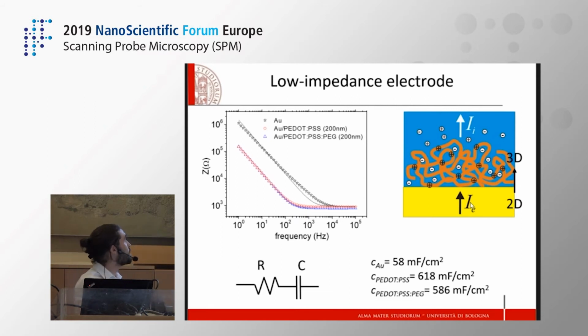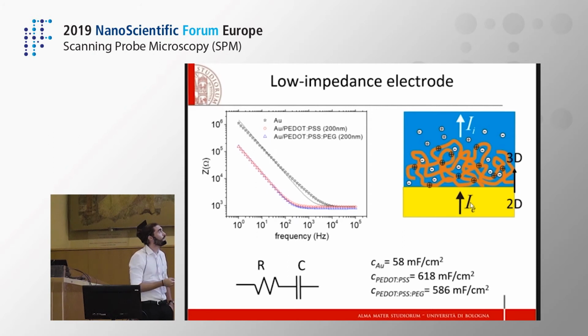In this case, this translates in the impedance into a lowering of the impedance and also an enhancement of the flat area of the response of the electrode, in particular in the area between 100 Hz and 3 kHz that is interesting for bioelectronic recordings. With the addition of PEG, the curve is almost the same. We had just a reduction of the value of the capacitance per unit area.